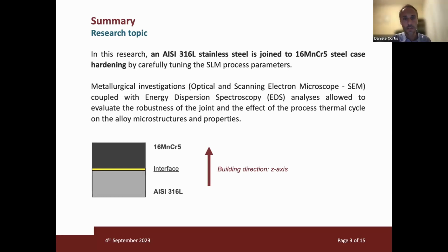And here we try to understand the behavior of a simple junction between the most common stainless steel that you can print with SLM, that is the AISI 316, in this case low carbon, and another standard case hardened steel, the 16MnCr5. And here we study the joint of these two materials with metallurgical investigation, with optical and scanning electron microscope, and also we did energy dispersive spectroscopy together with an evaluation of the micro-hardness of the junction. So as I reported here in this picture, the most important part of the junction, of course, is this interface between the different steels.